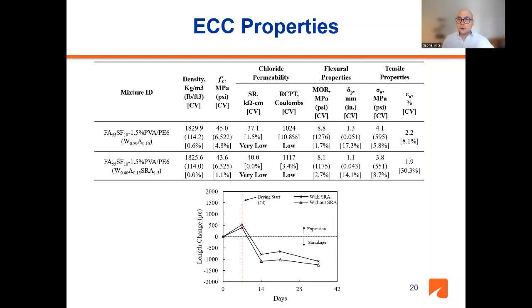Finally, I want to present also some shrinkage data results. This is not included in the table. And as you can see, when you use this shrinkage reducing admixture, you can reduce the shrinkage of these systems a little bit. These materials have a lot of cementitious content, so they tend to shrink a lot. This is not a concern with regards to cracking, because these are such ductile materials that they will not crack because of shrinkage. But it is important because we want to limit the shrinkage to prevent any type of bond problems with the existing metal pipe, right?